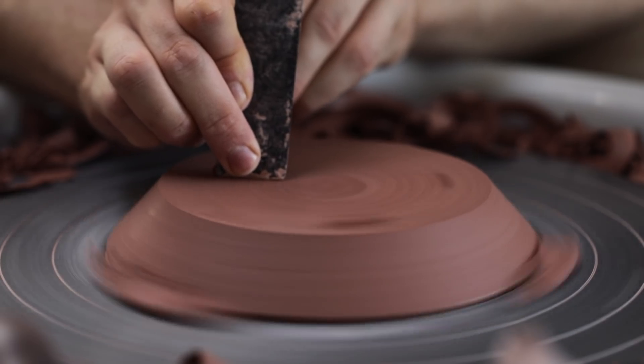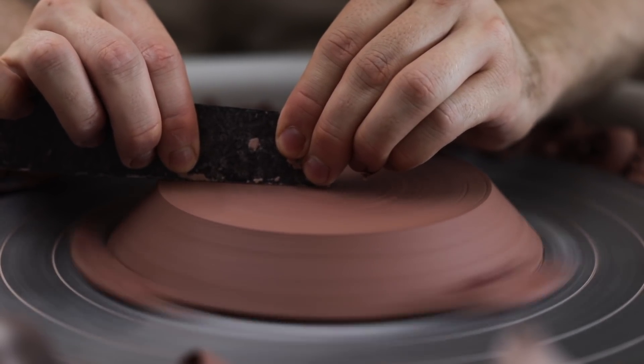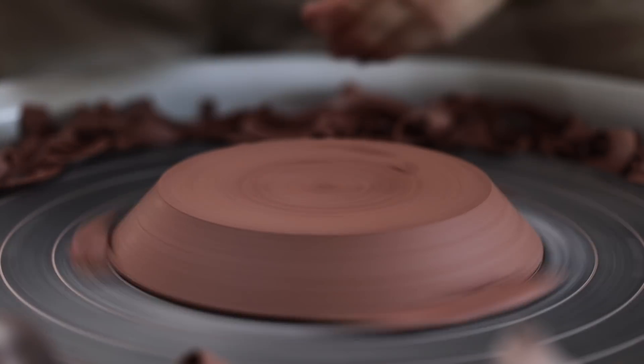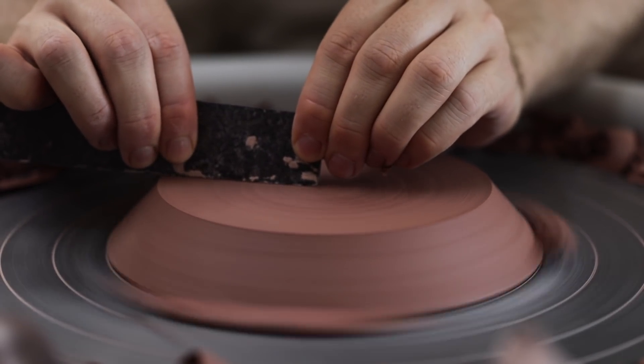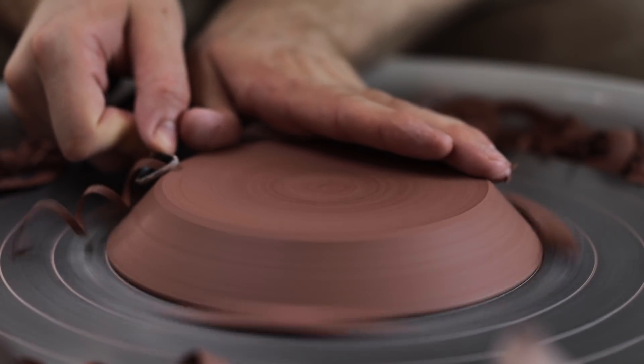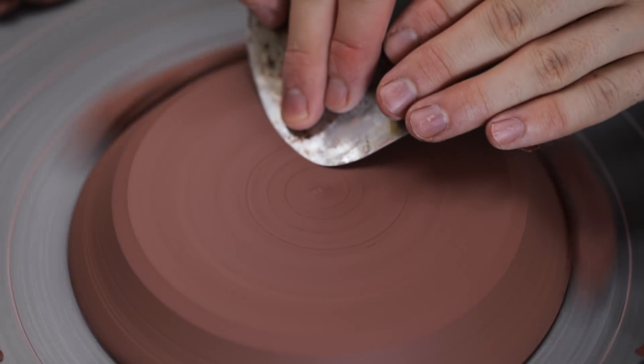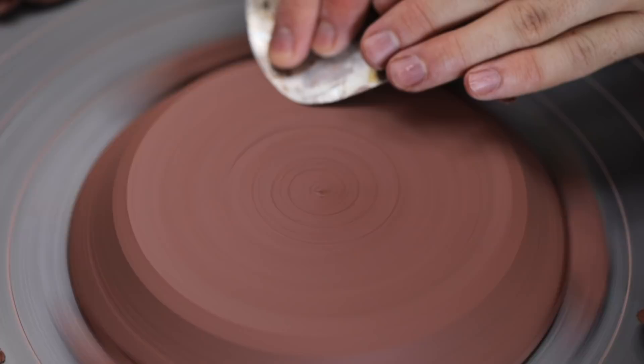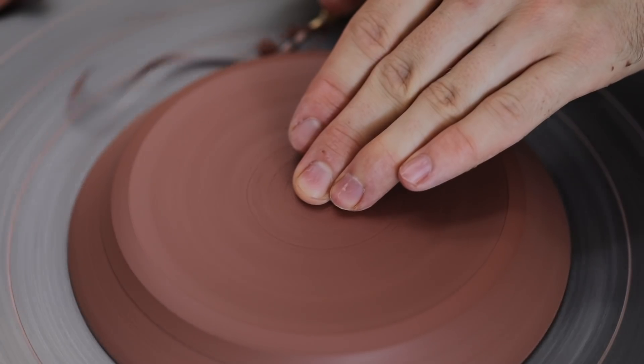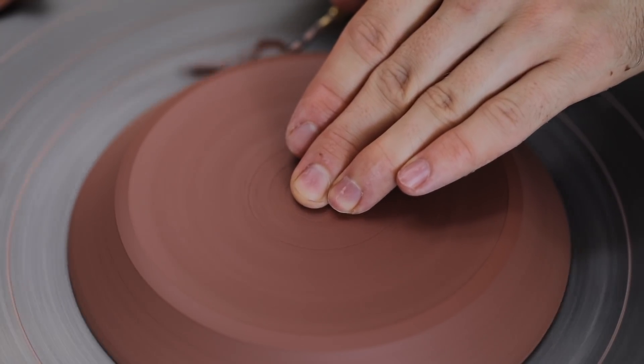That smooth consistency is similar to what I'm aiming for when trimming the bases, although I do still quite like the contrast between a slight roughness of the fired clay compared to the smooth glassy glaze that surrounds the rest of it. I quite like that the clay has a stone-like texture once fired. All I do once the piece has been through the kiln and fired up to 1290 degrees Celsius is very gently sand the base with some soaked wet and dry sandpaper, really just to remove the sharpest grains of sand that may still be protruding, because even though I burnish at this stage until it feels incredibly smooth, as the clay fires it shrinks and recedes around grains of sand and specks of grog, thus becoming sharp once again even on areas that were burnished to be glassy smooth.